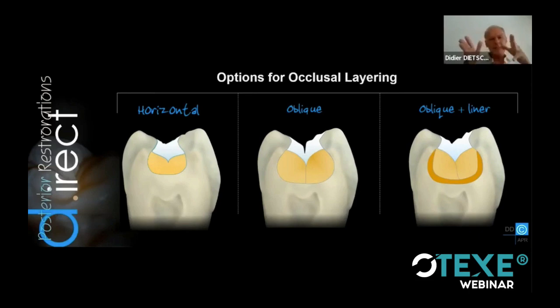But the basic protocol that I still have today in 2020 is to use a classical composite, such as a classical microhybrid or modern nanohybrids. Small volume. Now, when it comes to the occlusal part of the cavity, small volume, normally I bilaminate, dentin and enamel. If I have a little bit larger volume, I might use an oblique approach or vertical approach. So it means two different oblique increments for the dentin, always one single step for the enamel. And if it is even a little bit larger, I might use first a liner, flowable composite, then I might go with oblique layering, and finally enamel for the occlusal. And this, of course, relates to the volume of the restoration.